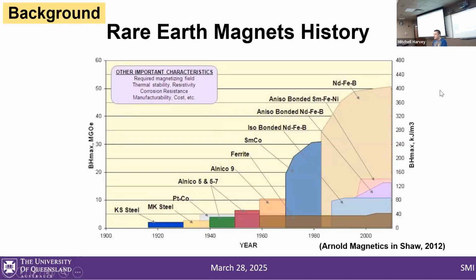So in the early 1900s, we had KS steels and MK steels. These are tungsten cobalt steels. They weren't particularly great magnets, but they were the first attempts at strong permanent magnets. And then in the late 30s to early 40s, we discovered platinum cobalt. As you might guess, platinum cobalt was very expensive and only saw limited use, but it was the best technology at the time. And it is unique among all the magnets pictured in this graph in that it's actually ductile.